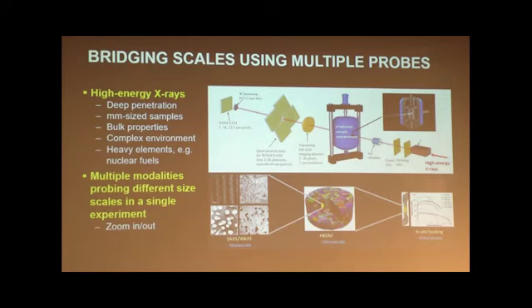This is just to give you an example of how we can do in situ multi-scale experiments using high-energy X-rays. I really think high-energy X-ray has a particular advantage when we look at nuclear material because of its deep penetration. And also because high-energy X-ray allows us to look at a large size sample, when we measure the sample, we can measure the bulk property, which is very important. And for studying nuclear fuel, because the fuel is a heavy element, you also need to have a high-energy X-ray. So this shows you the example.